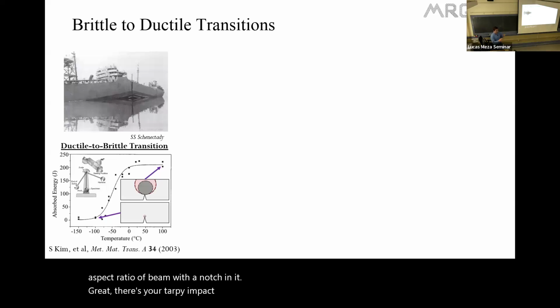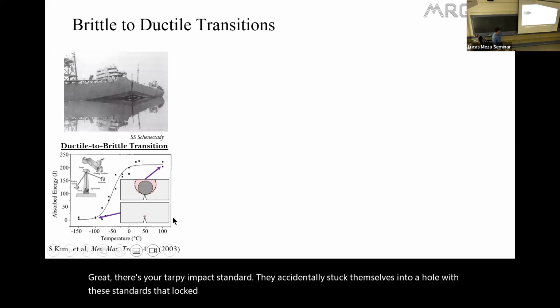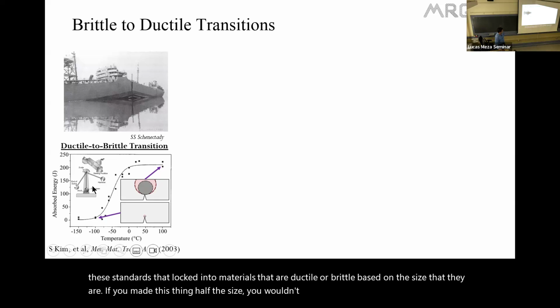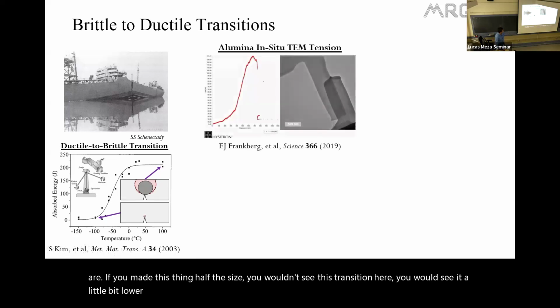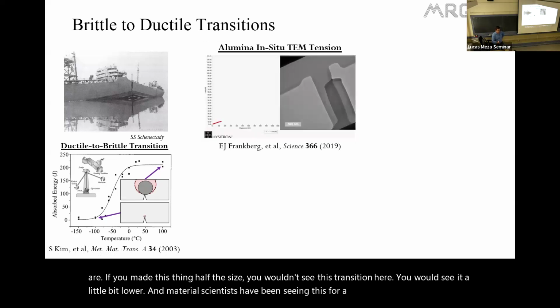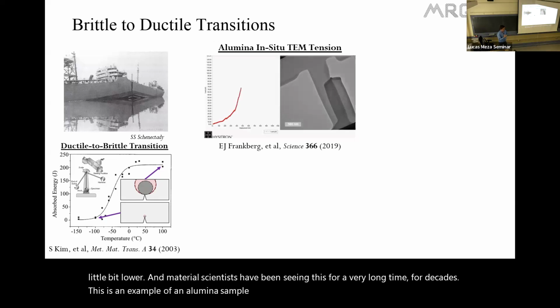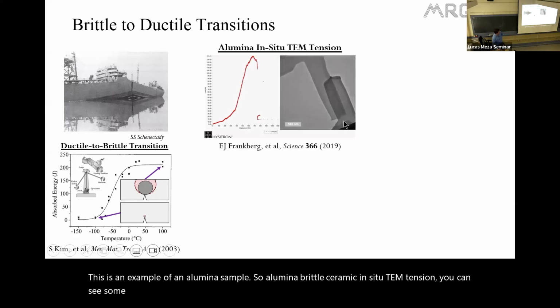They accidentally stuck themselves into a hole with these standards that locked into materials that are ductile or brittle based on the size that they are. If you made this thing half the size, you wouldn't see this transition here, you would see it a little bit lower. And material scientists have been seeing this for a very long time, for decades. This is an example of an alumina sample, so alumina brittle ceramic, in situ TEM tension. You can see some ductility there and actually a necking prior to failure.